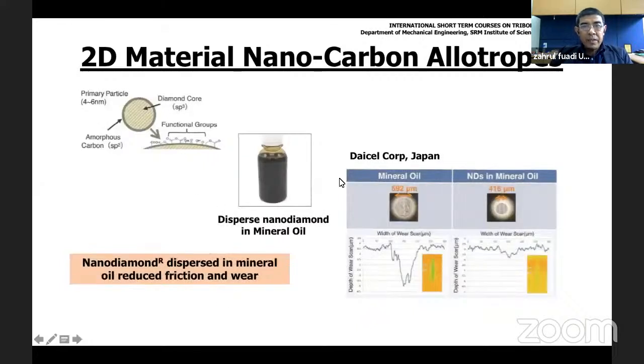For example, here from Daicel Corp Japan, they have produced so-called nanodiamonds. So these nanodiamonds can be dispersed in mineral oil. Then here, without the nanodiamond, you see a lot of pits, deep pits here, but with the nanodiamond dispersed in mineral oil, the wear is very much reduced.